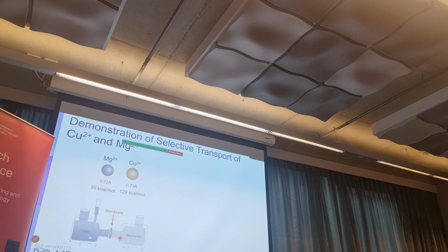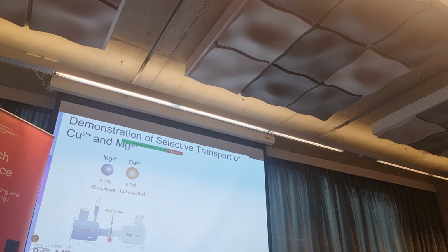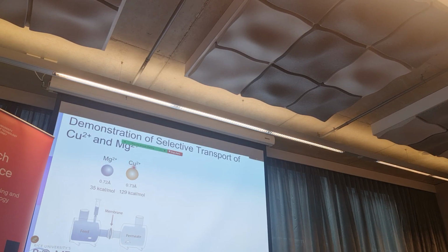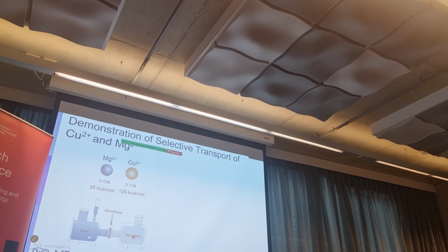We do experiments with a diffusion cell in which we create this membrane I mentioned, placed here. Here's the feed. We do it at low pH, so the copper will be copper 2+, and this is more like DI water, so the solute will go by osmosis to here.